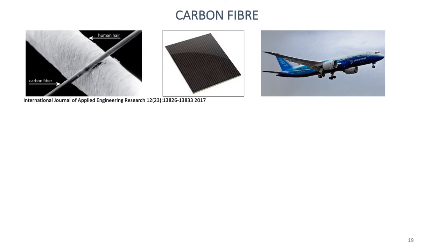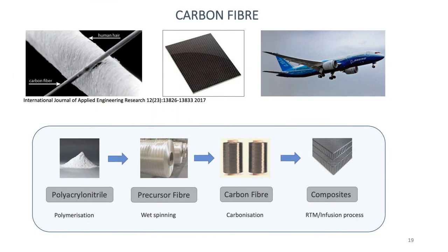Carbon fibers are synthetic fibers — important materials in areas where weight reduction and strength are necessary. When we compare the size of carbon fibers, they are around 5 to 7 microns in diameter, which is 10 times smaller than human hair, but about 8 times stronger than steel. The starting material for production of carbon fiber is a synthetic polymer called polyacrylonitrile or PAN. This PAN undergoes a process called wet spinning and forms a white fiber or precursor fiber. These precursors undergo high-temperature treatment over 1000 degrees to form carbon fibers, which are later used to make structural composites.